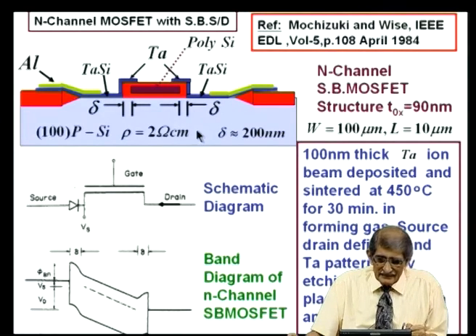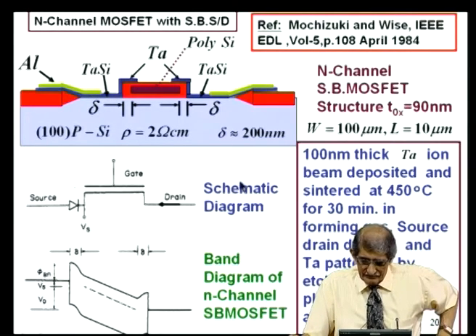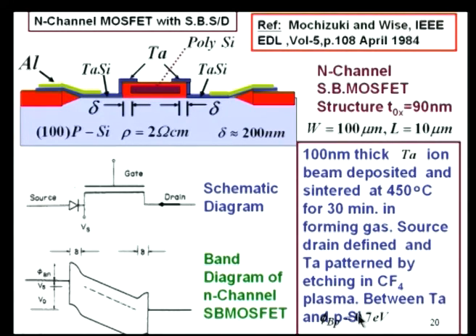So, what they did here, they fabricated N channel devices. They used tantalum. Phi B p is 0.7 electron volts. The phi B p is large there, phi B n is small there. So, they were hoping that they can just have some sort of Schottky barrier. So, they made it the same way they have done the thing. You can see the N channel Schottky barrier MOSFET structure, T oxide 90 nanometer, L 10 micrometers. They do not want to worry about short channel effects, etcetera.